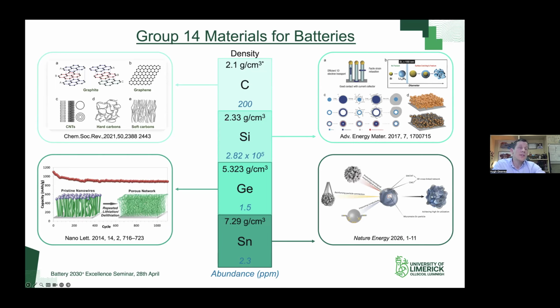And then with tin, again, tin has found applications both in lithium-ion and sodium-ion applications. You'll see straight away from comparing it to the rest of the group 14 elements that it is significantly more dense. Okay, so we're up here about 7 grams per centimeter cubed. So from a volumetric capacity perspective, tin has some clear advantages there as well. And for example, tin is active in sodium-ion cycling, whereas silicon is not. So what we have within this group is some nice overlap in properties, and then some interesting material linked properties, like, for example, what we saw in germanium.